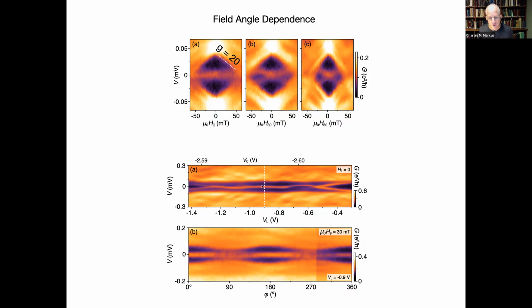You see that if you go to a place where it's not just about to split, nothing happens. It kind of changes the gap a little bit as the magnetic field goes transverse to the wire. But more or less, if you're along the wire in either of the two directions and you don't affect the gap, the zero bias peak persists all the way through. And here it is persisting also as a function of gate voltage, although splitting in places and rejoining in other places.